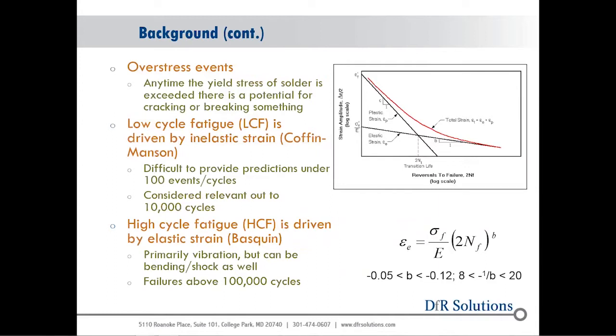As I said, anytime we hit the yield stress of the solder joints, even the yield stress of the copper leads or any other metals on the circuit board, there's a good chance we're going to break something. One of the things about electronics is that a lot of the fracture strengths of the materials are all very similar. So ceramic capacitors crack usually between 30 and 60 megapascals, maybe 80 megapascals. Pad cratering is around the same type of stress level. And then the yield stress of the solder is actually 30 to 50 megapascals. So you can imagine, as soon as I start yielding a solder joint, there's a good chance I'm going to break something.